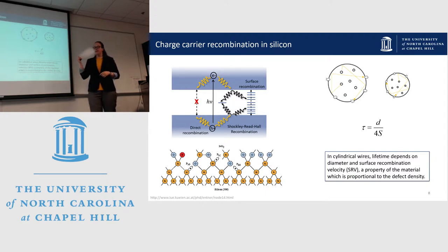And in a silicon nanowire, this happens predominantly at the surface, right? So the wires that we have are really high quality, which means that the silicon in the bulk of the wire is very, very pure. But the surface is exposed to oxygen, it has a lot of dangling bonds, and so that's where you get a lot of these defects.